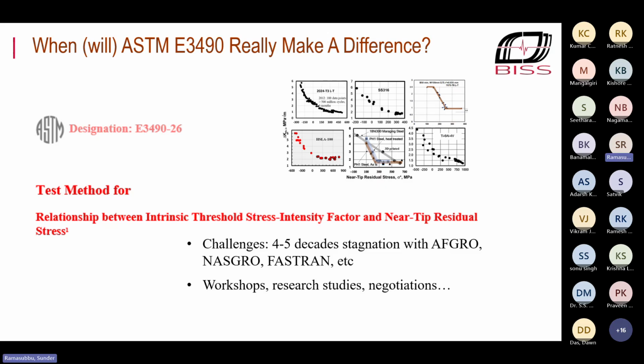So, if you look at the gust statistics, when the load gust amplitude comes down by half, the number of cycles at that lower amplitude goes up by a factor of 10. Therefore, the smaller and smaller cycles will keep exponentially increasing in number. Whereas the Falstaff spectrum is for a fighter aircraft. For fighter aircraft, the loads are mainly from maneuvers. Turbulence doesn't make a dent on a fighter aircraft. But if you look at helicopters, it makes a huge difference.